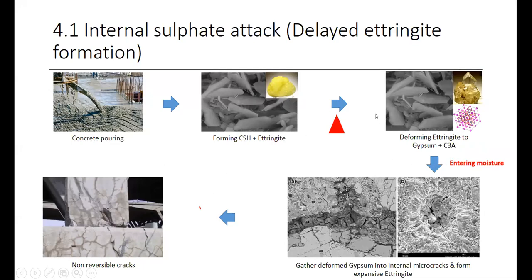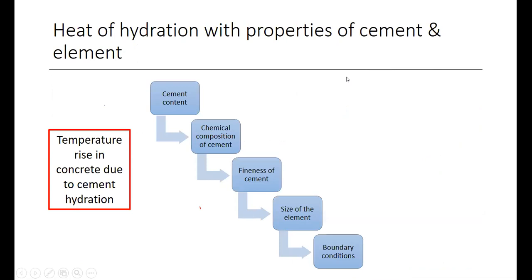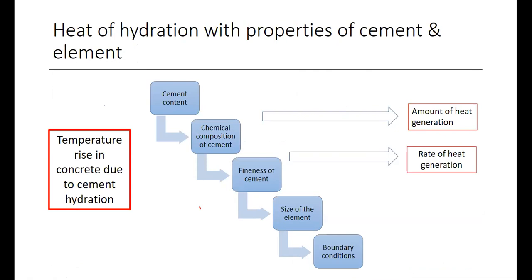And if there is an issue of high temperature, then the best thing we have to do is eliminate the possibility of moisture ingression. It's a bit of a hard task. We know precautions are always better than acting at later stages, so we have to take precautions to eliminate the risk of high heat generation. Then we have to identify how the heat is generated with the cement. The process engineer's task is basically this. With the cement content, if we put in more cement, it will generate more heat. And with the chemical composition, if the cement has more C3S or C3A, there will be more heat generation.